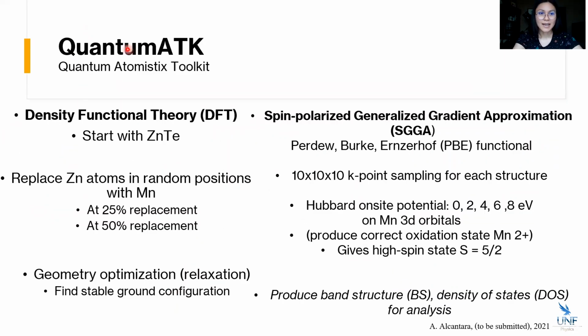So we analyze the system using QuantumATK, using density functional theory. Because there are so many electrons, it can't be calculated manually. And what DFT does is it examines how the electrons move through a material. And so we started with a zinc telluride structure, and we replaced the zinc atoms with manganese at 25% and 50%. We use a geometry optimization to relax the structure and to assure a ground state of antiferromagnetic, which is expected. We use the spin-polarized generalized gradient approximation and the PBE functional for a fairly large K-point sampling to properly model the system. We show that a Hubbard on-site potential is necessary to achieve the proper manganese magnetism on the 3d orbitals. And this is for that high spin state of 5/2.